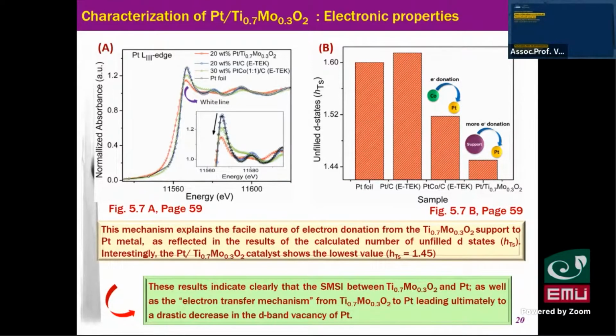But in our support material, the titanium molybdenum oxide, we found a very interesting mechanism: electrons are transferred from the titanium molybdenum oxide support to the platinum metal. We measured XPS to show the electronic property here. Compared to the commercial catalyst, which doesn't show any electron transfer from carbon to Pt, in our catalyst we found electron transfer from the titanium molybdenum oxide to the platinum. That means there is a very strong interaction between the support and platinum.